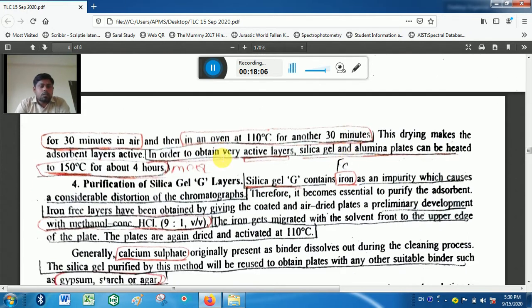In order to obtain very active layers, silica gel and alumina plates can be heated at 150 degrees Celsius for about 4 hours. Remember those data for the purpose of MCQ.